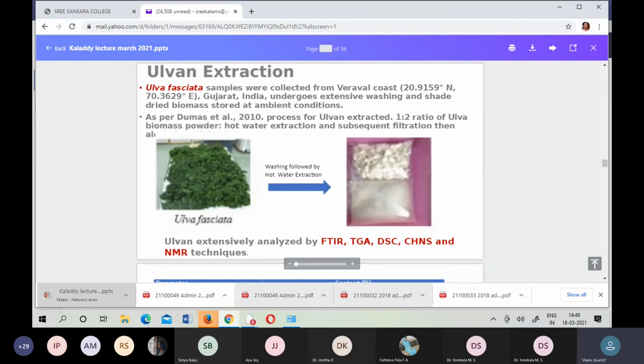We were coating the same Ulvan on polymer surface because the polymer membranes are facing the fouling problem. We try to coat this material because it's a sulfated seaweed polysaccharide with uronic moiety, and we were able to control the fouling by using this.